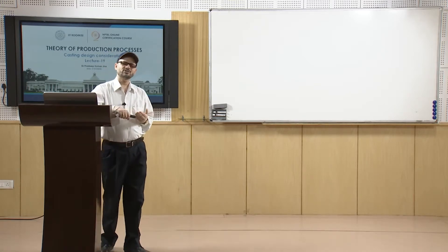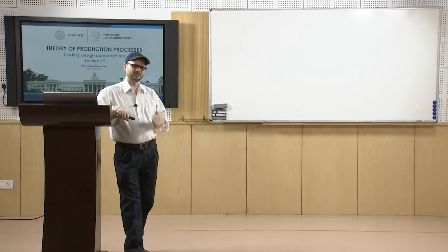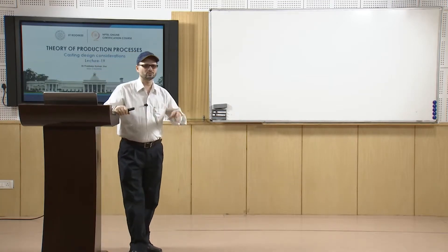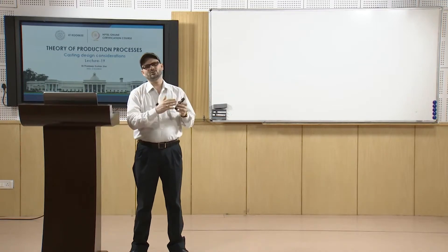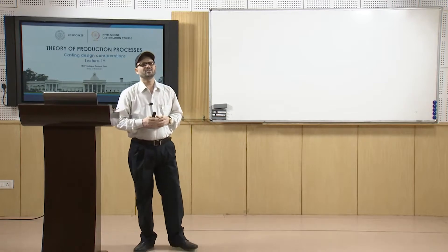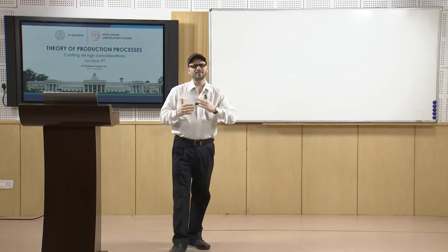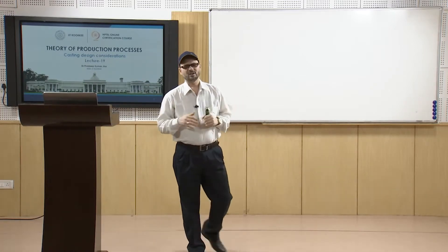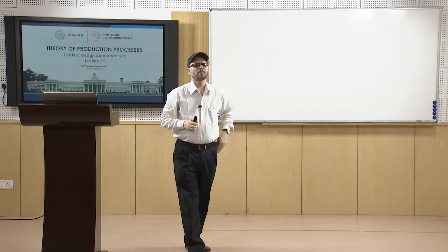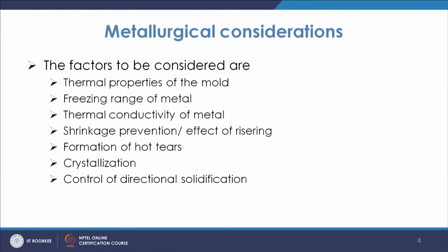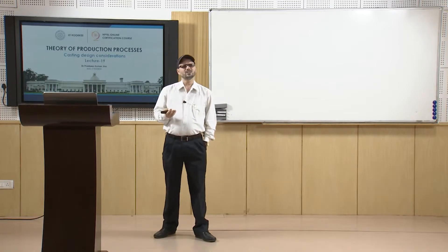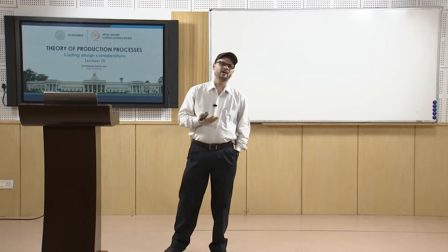You will have to have proper practice — adequate positioning of risers and adequate size of risers — so that even for materials with a higher freezing range you can control these parameters. Casting quality is also affected by thermal conductivity of metal, which affects the solidifying pattern by guiding the temperature difference or temperature gradient inside the liquid metal pool. Shrinkage prevention through proper risering is another point — using risering you can decrease the chances of shrinkage, and you must have proper risering calculations.